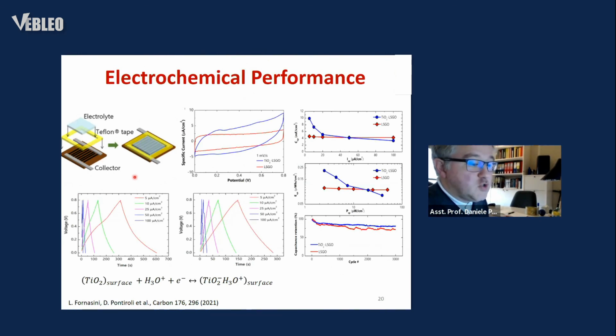The interdigitated symmetrical supercapacitor has been assembled following a standard protocol displayed in this picture. And the devices were tested with cyclic voltammetry and galvanostatic charge-discharge measurements. And we found that the presence of titanium dioxide nanoparticles almost doubled the capacitance of the devices, thanks to the presence of pseudocapacitive effects on the titanium dioxide nanoparticle surfaces, reaching the noticeable specific areal energy of 0.22 microwatt hour per square centimeter. And also the capacitance retention in these systems seems to improve as compared with bare graphene systems, as observed by testing the devices for over 3,000 cycles.